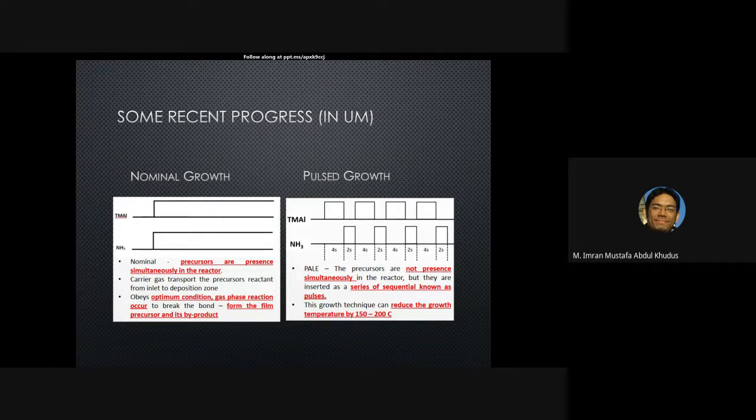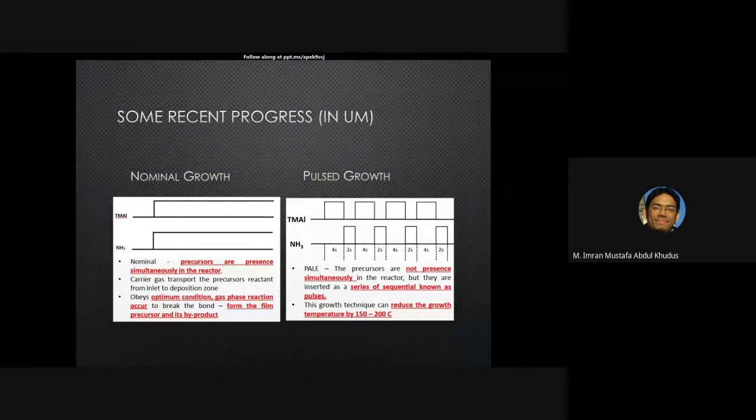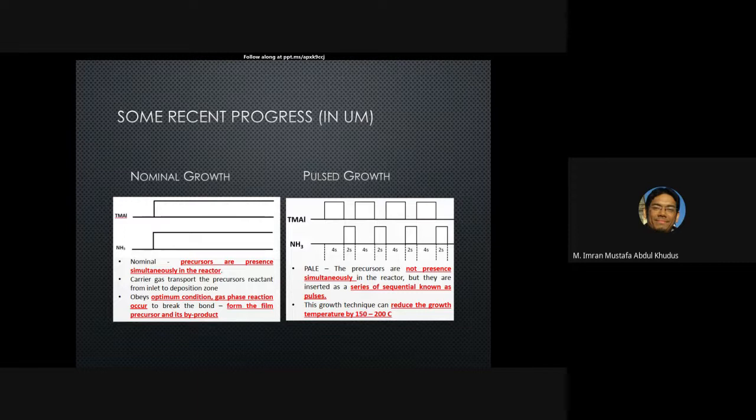But yeah, if anyone is interested in collaborating or anything like that, we do have these projects on, and we have a second MOCVD which should be turning on fairly soon. We need the engineers to come in, and that second MOCVD should be able to do what USM is doing. One of the reasons why we did pulse growth is because our reactor cannot go to the temperatures at which aluminium nitride is best grown. Pulse growth allows us to reduce the temperature. But the new reactor that should be coming online soon, hopefully, is capable of those temperatures.